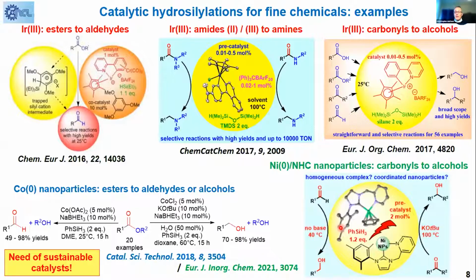Switching to catalytic hydrosilylation for fine chemicals. This is mainly the job of homogeneous catalysts, and we have done in the past various examples using precious metal catalysts, like those based on iridium metallacycles shown here. These metallacycles are very active for the hydrosilylation of esters to aldehydes, so chemoselective reduction of esters to aldehydes. We could also reduce secondary and tertiary amides to amines with turnover numbers up to 10,000. And various carbonyl derivatives, from carboxylic acids, esters, ketones, aldehydes, were converted to the corresponding alcohols in mild conditions and in a straightforward way.